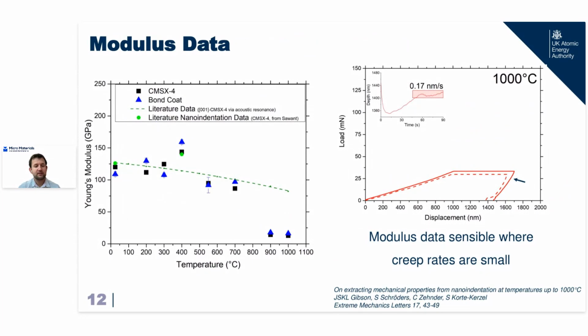So that kind of explains the hardness data. What about modulus data? Well, that kind of turns out fine most of the time. For up to 700 degrees, where creep rates are relatively limited, we're pretty much bang on with literature data. At 900 degrees or 1000 degrees, we're measuring nonsense. There isn't another way to put it.